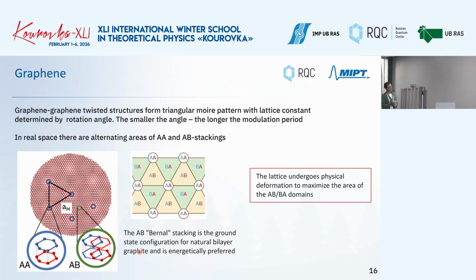And you see that there are large triangular areas where there is a stacking like this, and just a few points where the stacking is like this. So there is a physical deformation to maximize the real area of this domain. When you put one on top of the other, in real life these domains will form a little bit more, so they will organize themselves. So these areas with low potential energy will be larger.